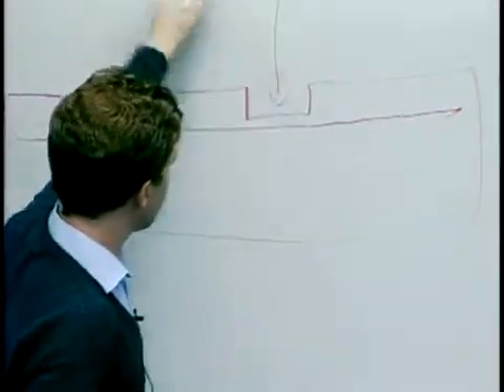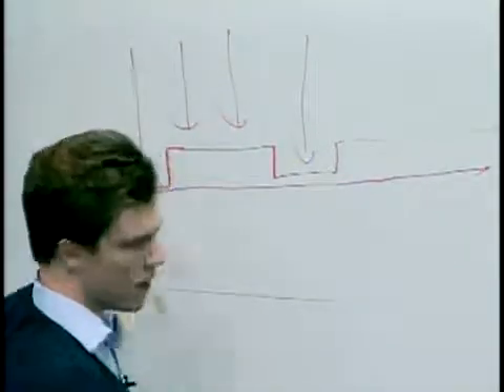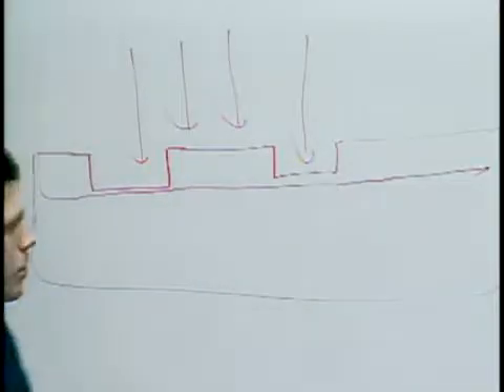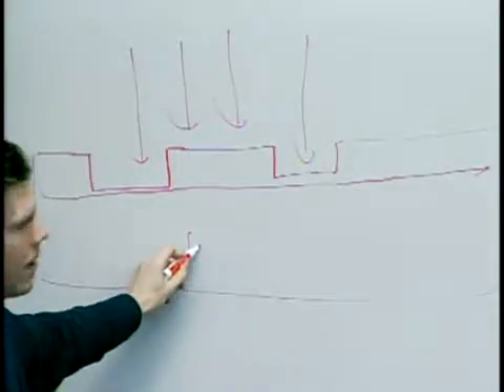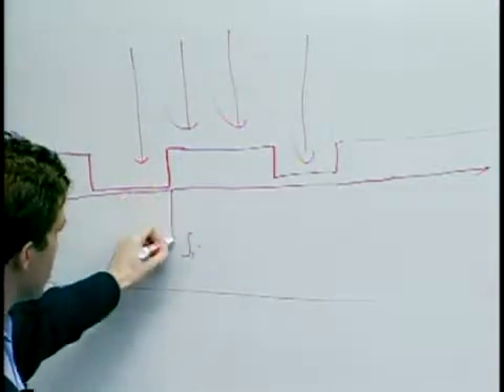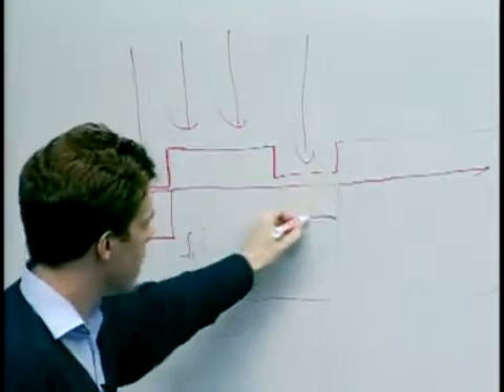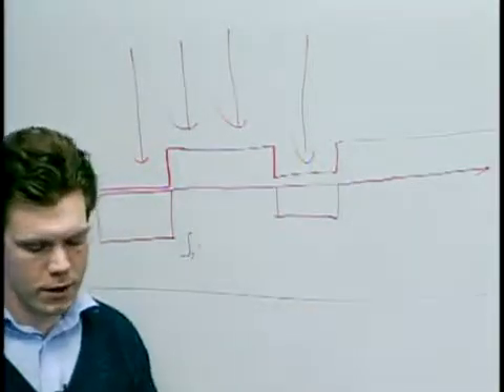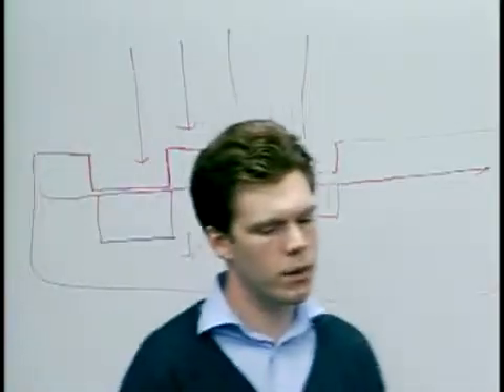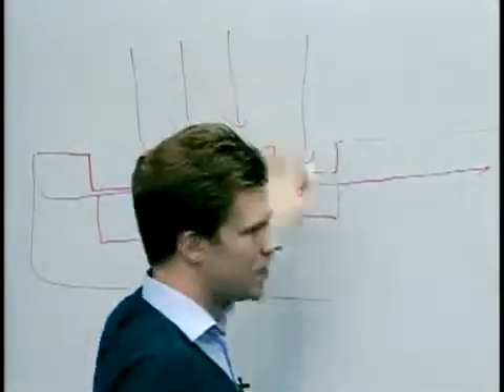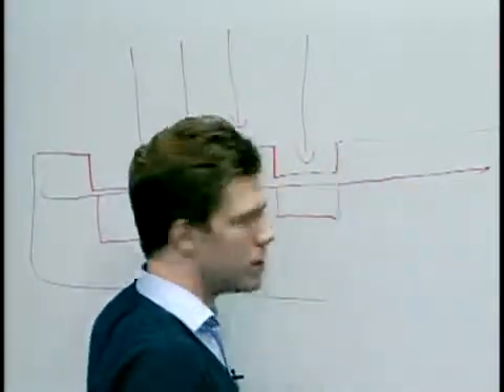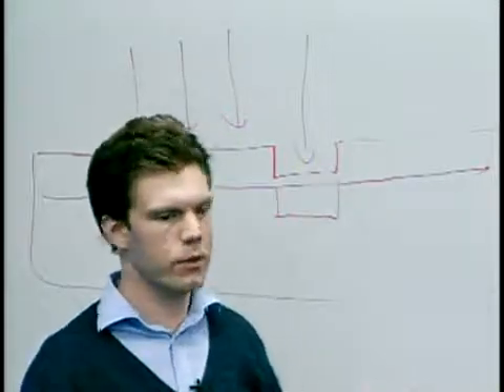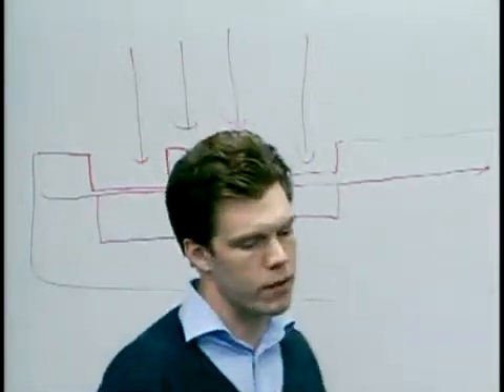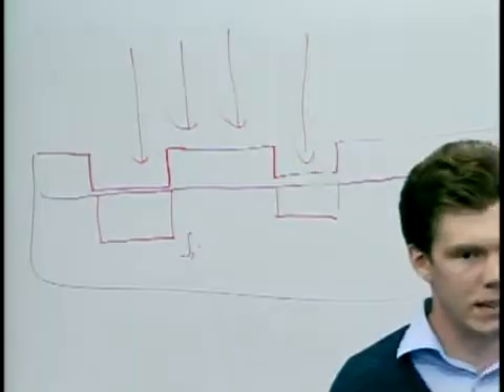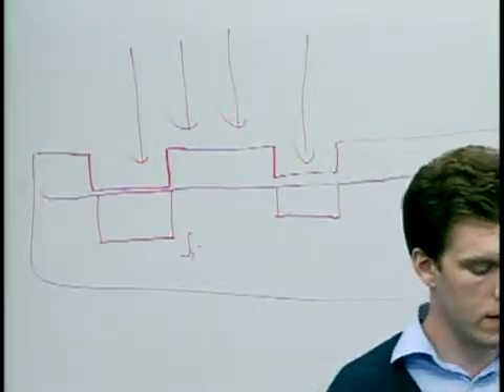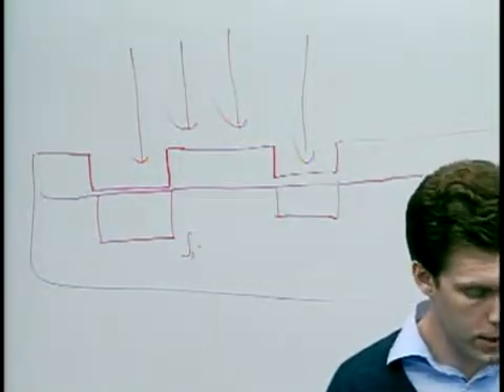You then expose this with a fluorine plasma. You're trying to etch the silicon underneath here. You're going to end up with a deeper trench here than you are here because of the time it took to get through that. So coming up with ways of designing the stamp so that the residual layer ends up being as uniform as possible is a really pressing challenge, actually, for this lithography technique to be adopted.